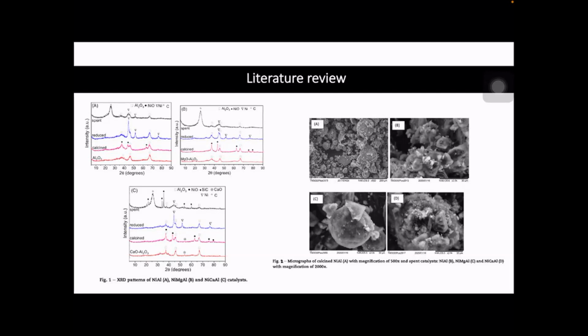Furthermore, a broad peak at 26 degrees was observed in all spent catalysts, related to coke deposition during the reaction. Nickel magnesium alumina catalysts exhibit the most intense peak, suggesting more significant coke formation.